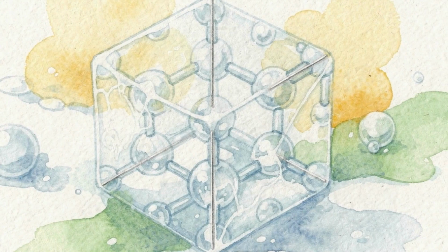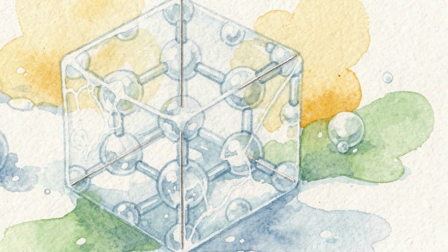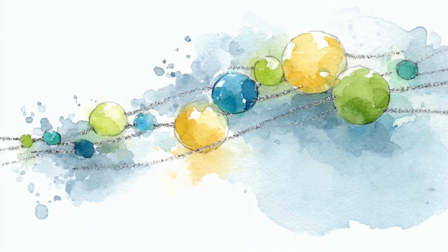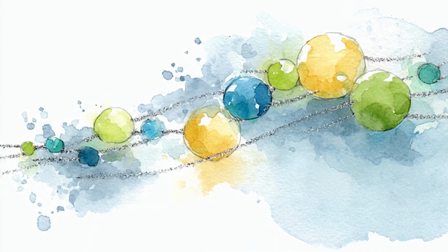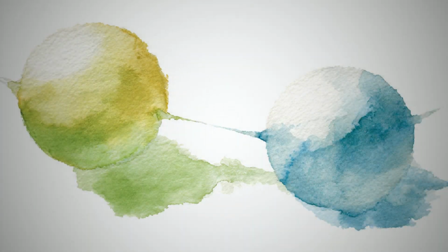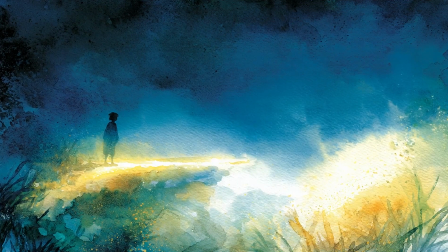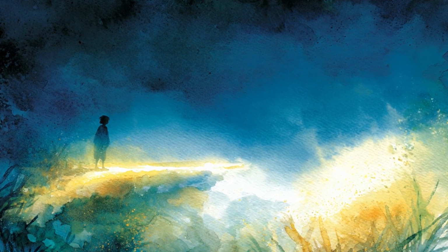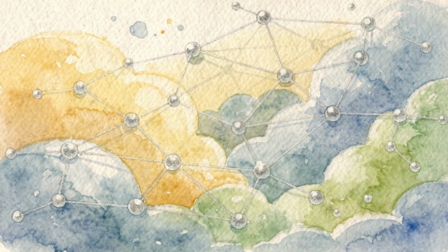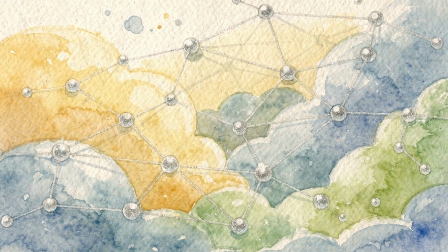At 250 Kelvin, the hexagonal crystal has unit cell dimensions of 4.5181 angstroms and 7.3560 angstroms in the c direction. These distances are so infinitesimal that the average nearest oxygen-to-oxygen distance is just 2.76 angstroms. Even the bonds themselves are microscopic. The hydrogen-to-oxygen and oxygen-to-hydrogen bond distances are 1.75 angstroms and 1.01 angstroms, respectively.